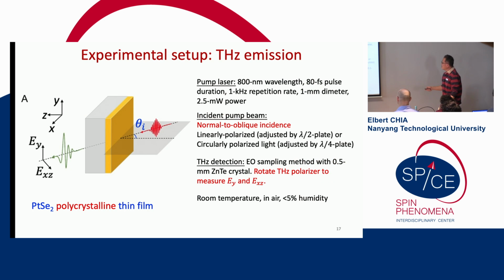And so we were able to pump the sample from normal incidence to oblique incidence. We were able to obtain not just the Y component or the in-plane component of the emitted Terahertz electric field, but also the out-of-plane component, which we call XZ. And take note that this platinum diselenide sample is actually polycrystalline, not a single crystalline thin film.